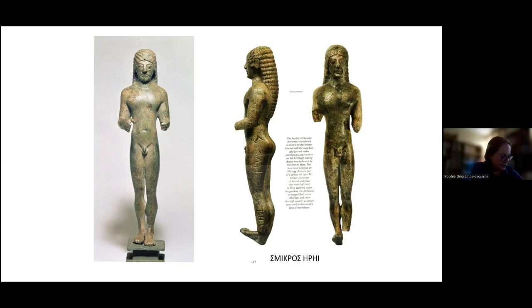Whether Smikros was looking at the finished bronze model, a wax model, or the original prototype, which could have been made of ivory, wood, wax, or terracotta, isn't clear. But this discovery sheds new light on the duplication of similar offerings by Samian bronze makers in the third quarter of the 6th century. As the clay in the partial master molds had to be dried and fired, the proportion of the original model must have been slightly higher.